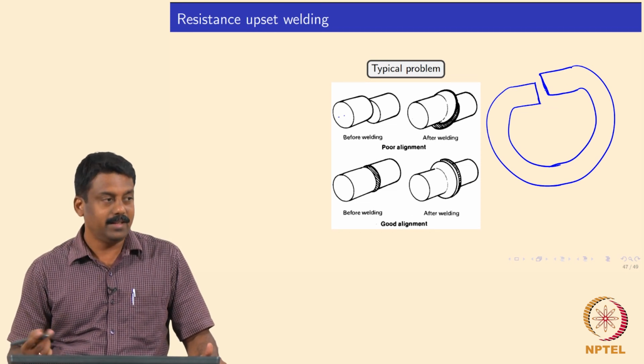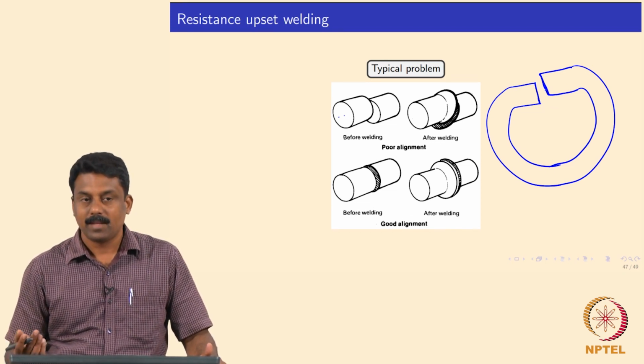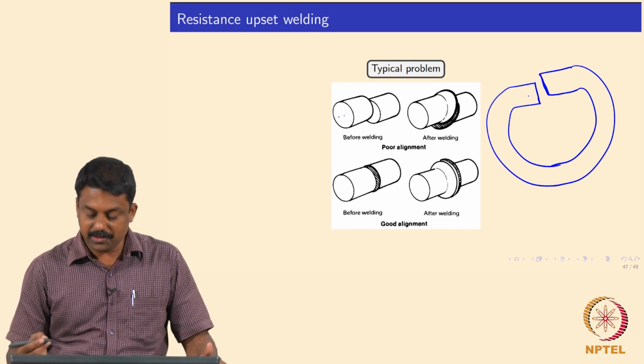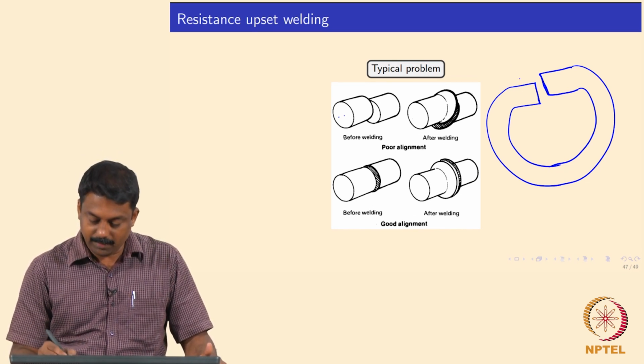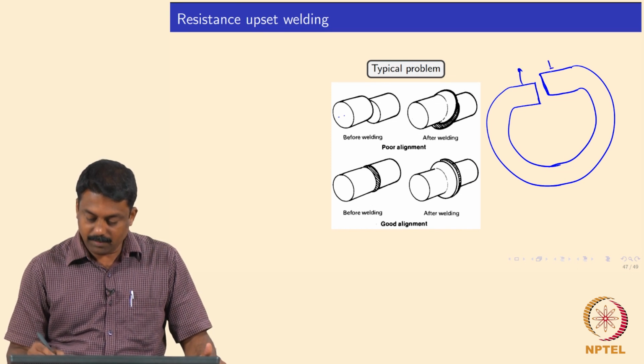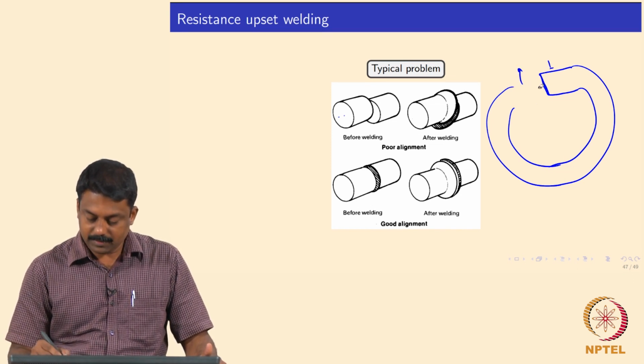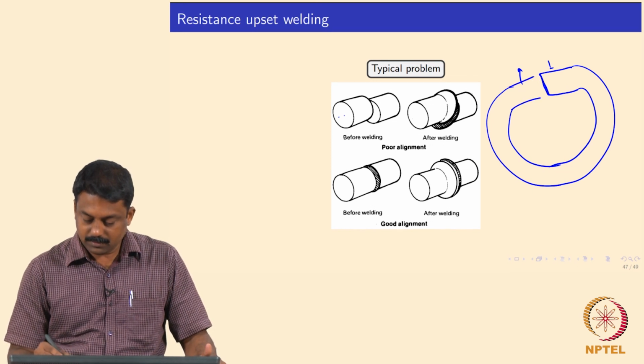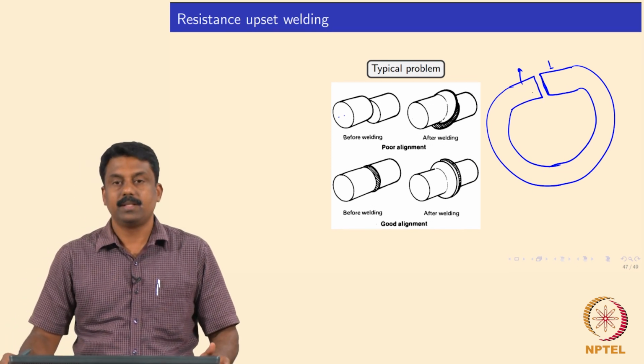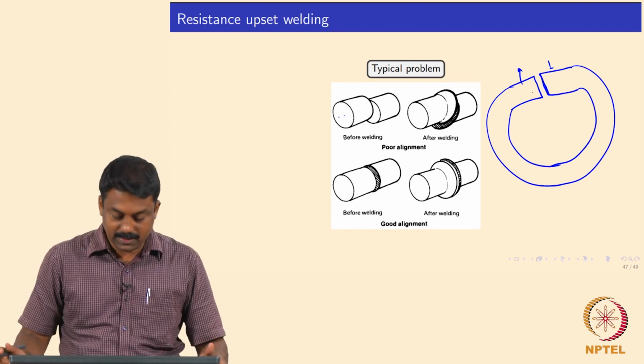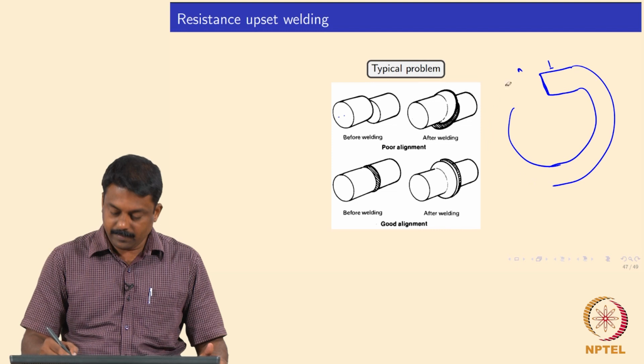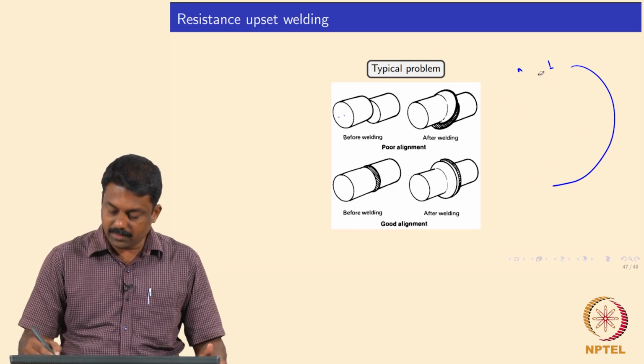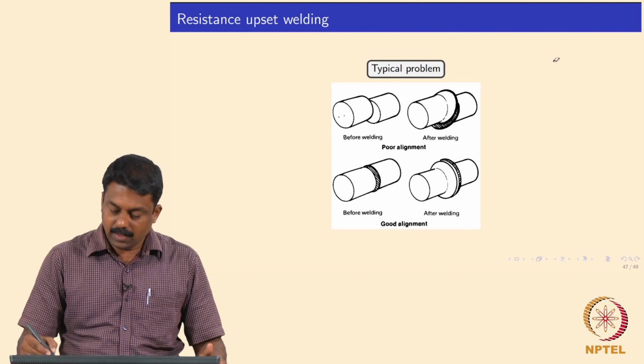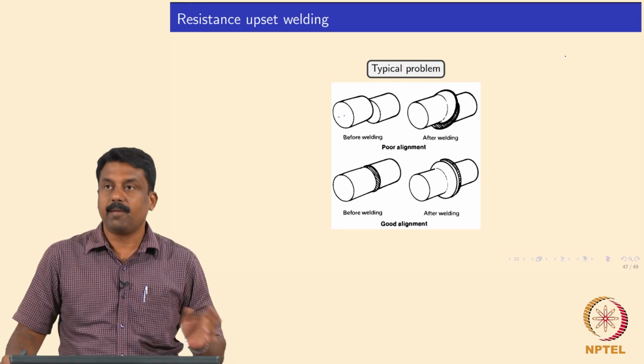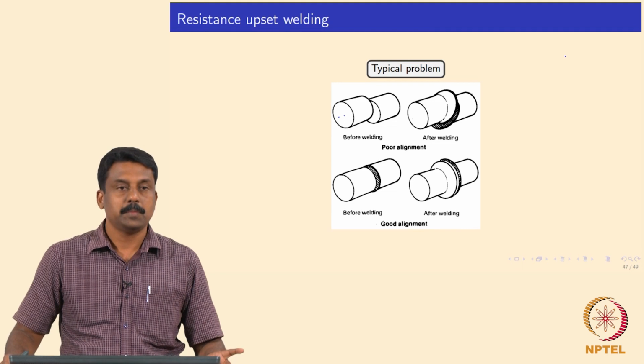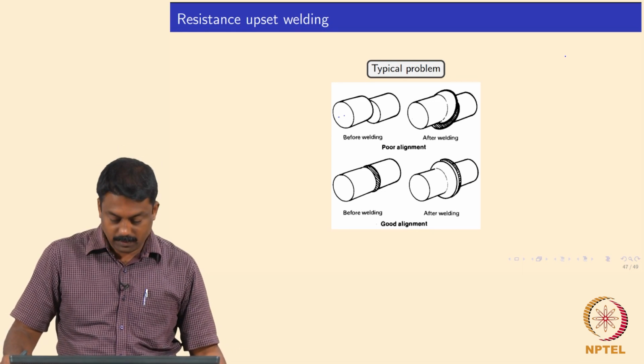So now if you are doing flash butt welding, the alignment will not be proper. So there must be an additional arrangement with the clamping, so that this can be pushed and this can be brought down, so that you will have a perfect interface, and then you can make a joint, right. So this alignment problem is very critical, and there are ways to overcome it. That actually comes from the equipment manufacturer, and these problems can be tackled very easily, right.